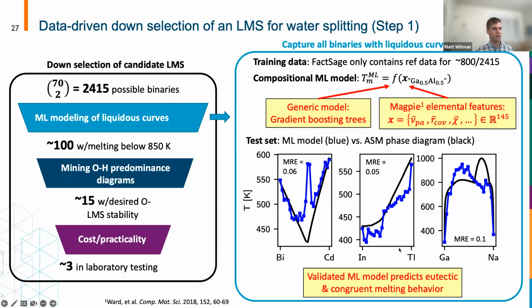And so for these binaries, you can clearly see that the model can capture these eutectic and congruent melting behaviors, and the mean relative errors across this entire composition space of the liquidus curve is actually not too bad. So that enables us to make sure that we weren't missing any materials from this initial FactSage data set.